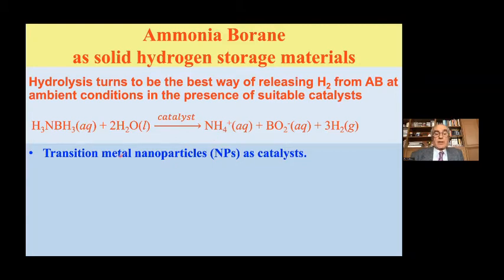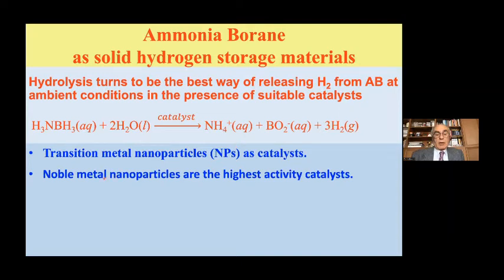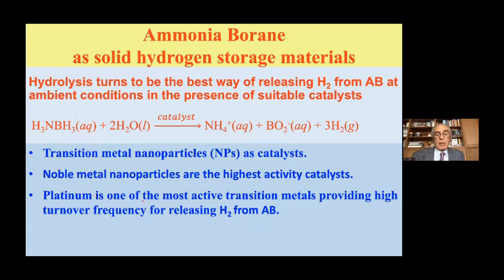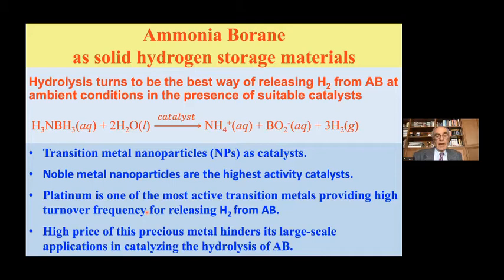Transition metal nanoparticles are the most commonly used catalysts in this reaction. But noble metal particles are the highest activity catalysts. Among them, platinum is one of the most active transition metals, providing high turnover frequency for releasing hydrogen from ammonia borane. However, the high price of this precious metal, platinum, hinders its large-scale application in catalyzing hydrolysis of ammonia borane. So we have to solve that problem.